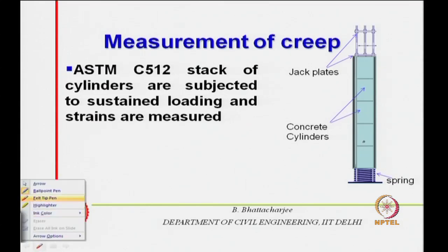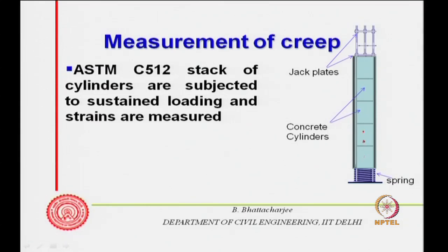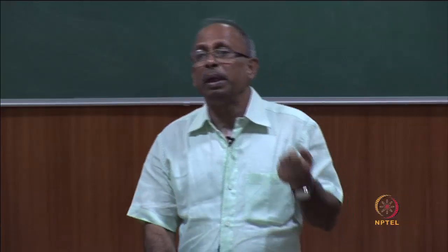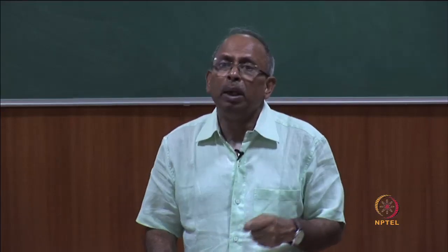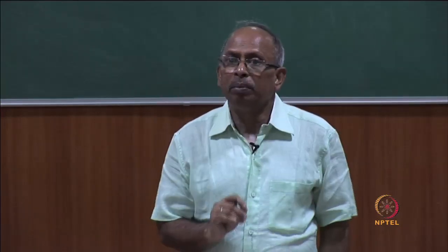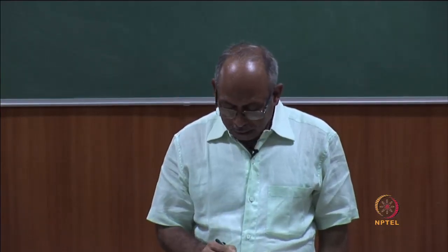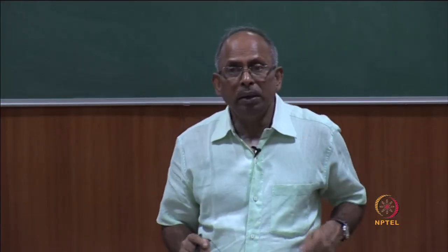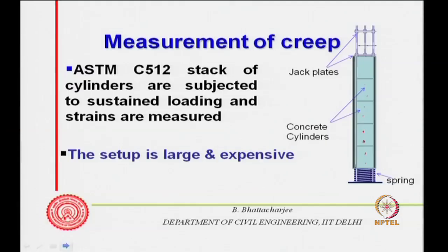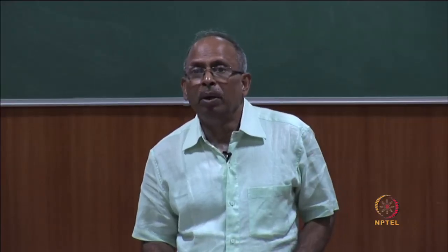You put strain gauges, and varieties of gauges have actually been suggested. You can have gauges in the central portion, you can insert them, put them on the surface, or even embed them. All possibilities are given in the code, and that is how creep is measured. Now this is costly. It is large and expensive, especially when you are trying to test a number of such cylinders, because it needs a loading frame. But it is possibly the only standard method available for measurement of creep.